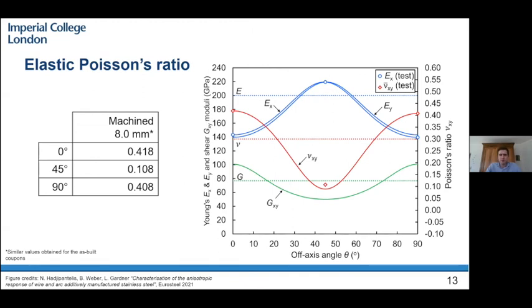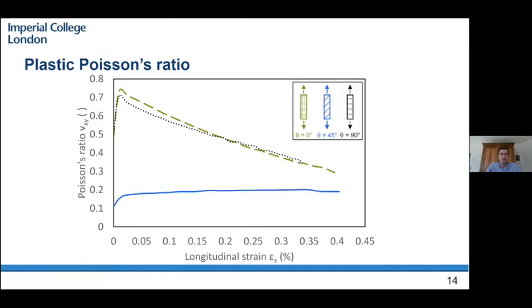However, the elastic material model is not sufficient to get a clear simulation of the material behavior. We also need the plastic behavior of our material. A first analysis was done for the plastic Poisson's ratios, which, against the assumption of a plastic Poisson's ratio of 0.5 for steel, are varying over the longitudinal strains, and there's also a clear distinction between the 0 and 90-degree and the 45-degree direction. But these varying plastic Poisson's ratios can also be seen in other orthotropic materials, such as orthotropic aluminum sheet metal, where it has been detected as well.